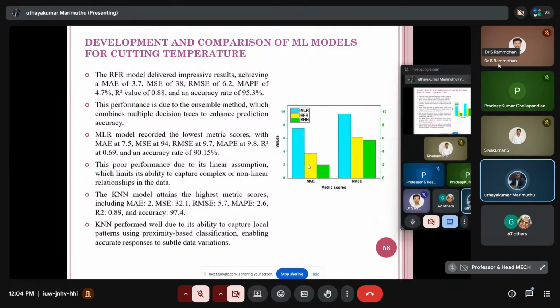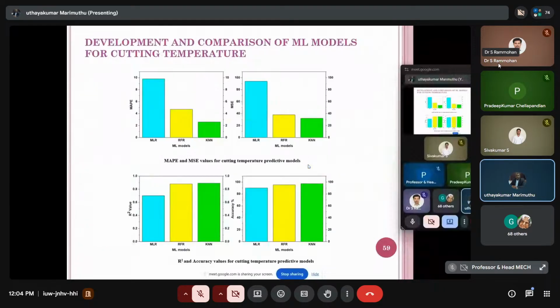This poor performance is due to the linear assumption, which limits its ability to capture complex or nonlinear relationships. The KNN model attains the highest metric scores, with an accuracy of 97.4. Here you can see RFR is 95.3, MLR is 90.15, and KNN is 97.4. KNN performed well due to its ability to capture local patterns using proximity-based classifications, enabling accurate responses to subtle data variations. So this is about the models and their comparison.